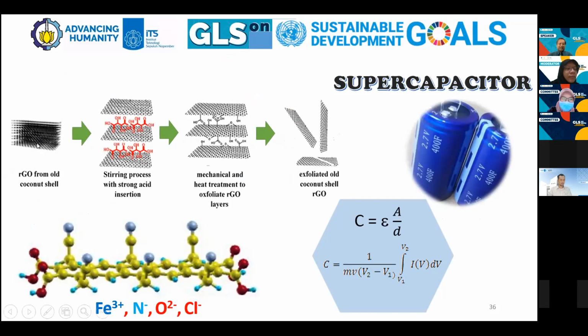You can see here that the graphenic-like carbon from coconut shell needs to be exfoliated. It means that it's divided into much thinner layers than before, to increase its surface area by injecting some glucose like this one, or hydrocarbon with short length molecule, either glucose or acid, during the process. Besides, the graphene sheet requires increasing the dielectric constant by attaching positive or negative ions like this, like iron, nitrogen ion, oxygen, and also chlorine ion.